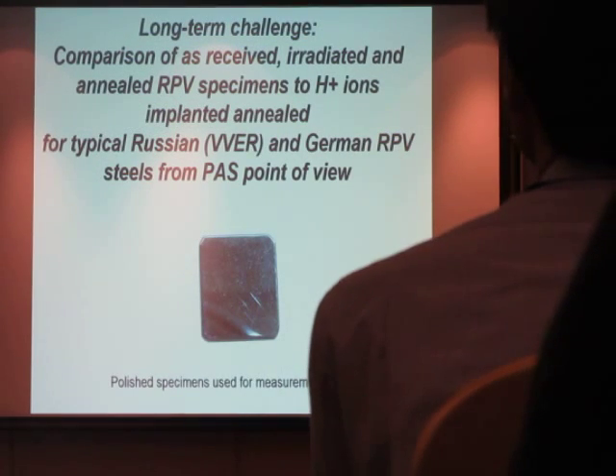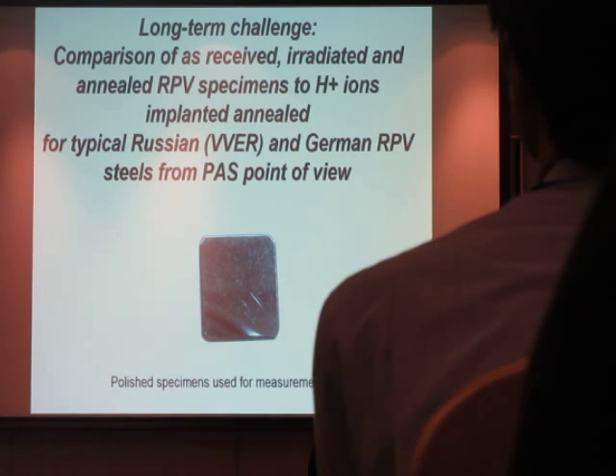Good. In the current research, we tried to compare German and Russian steels in 3 stages. Not irradiated, original irradiated by neutrons, and after that we compare these results with similarly treated materials, but where the treatment was done by hydrogen implantation.